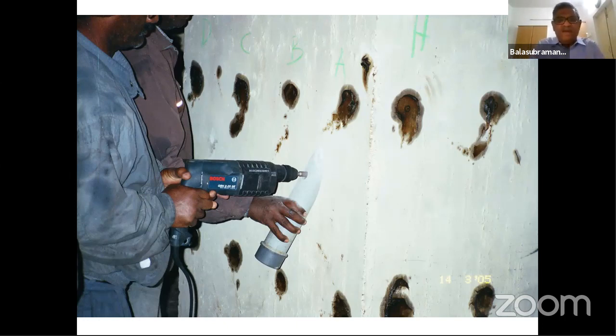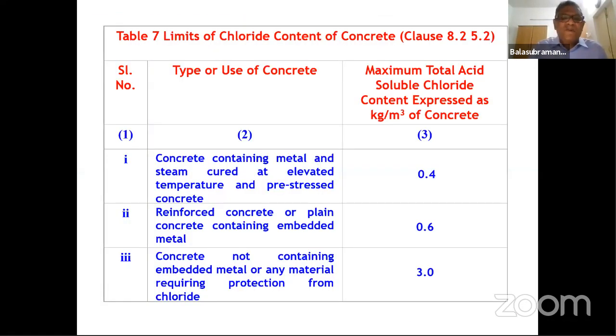Here, when I do it with a drilling machine, I cannot get a proper profile, because all of it is 0 to 20 or 20 to 30, even though I put a dryer and try to blow it off, it may not give me a perfect result, but it gives me some idea about the chloride content. The best way would be to drill a core and put it in a lathe with a chuck, and then use a tool. So you will precisely find out from 0 to 10 mm what the chloride content is, then 10 to 20. So you will know to what depth the chloride has penetrated for suggesting a proper rehabilitation methodology. But it is very sophisticated, so we go for these kinds of simple methods.